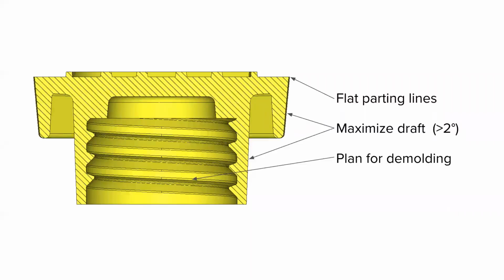Secondarily, maximize draft. We're going to come back to the demolding conditions, and any time that you can get excellent draft conditions, you want to get upwards of 2, 3, 4 degrees if you can. Then lastly, we always try and get an early plan for demolding. The sooner that you can figure out how you're going to get your part out of the mold intact and keep your mold intact, you'll get many more cycles out of your printed mold.